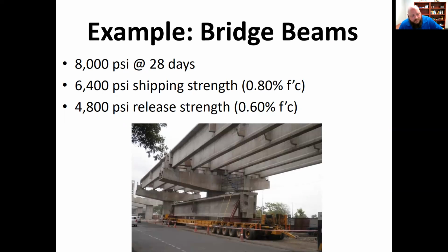So with something like a bridge beam, it may be that the bridge beam needs to be 8,000 psi at 28 days. However, for you to release the stressing strands after they pour that concrete, it needs to be at least 4,800 psi, which in this case is about 60% of 8,000. You also need to ship the beams, so for the beams to be not only released and moved to an area to be stored until it's ready to be shipped, but the shipping strength, meaning you can put them on the semi and drive it down the road, is usually at least 80% of the minimum compressive strength. So 6,400 is about 80% of the 8,000. So just try to realize that.